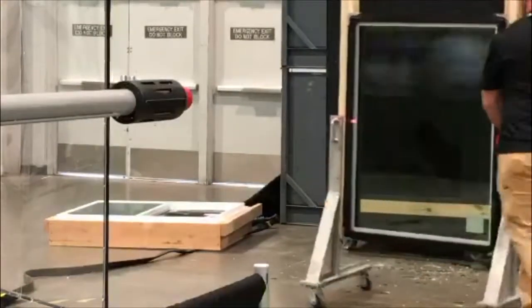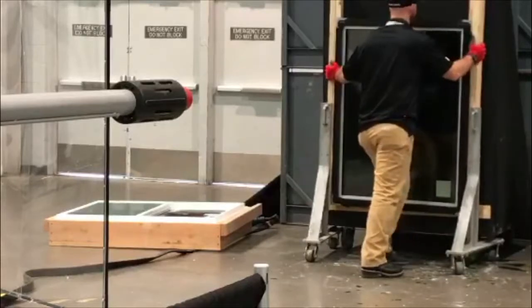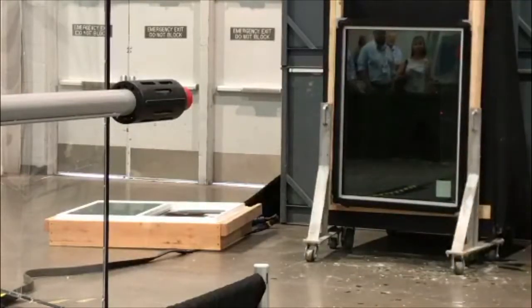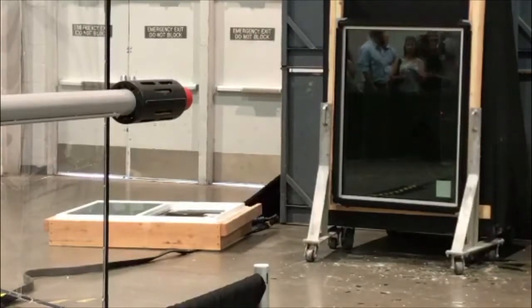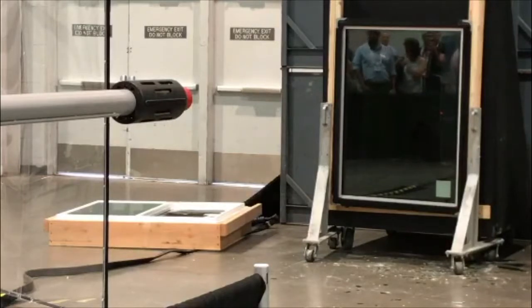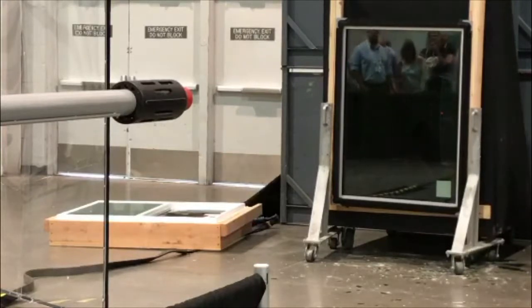Now what we're putting on the impact stand is an impact-resistant fixed window with insulated IG laminated glass. The window was provided to us by Western Window Systems. It's got laminated glass, just like the windshield of your car. It has a thicker interlayer. The glass itself is insulated — you'll see the glass break. It has a quarter-inch tempered sacrificial lite in the front, half-inch airspace, and then 9/16th laminated. The interlayer is a Kuraray SG. There are plastic interlayers, polycarbonate interlayers, and liquid interlayers for laminated glass — a lot of different options.